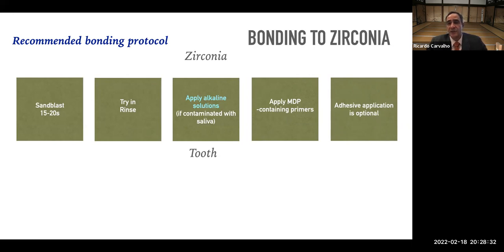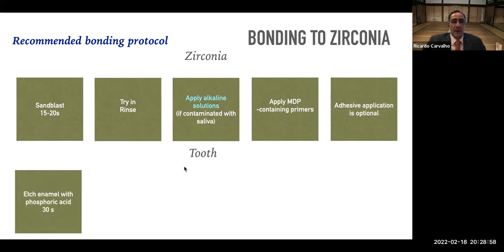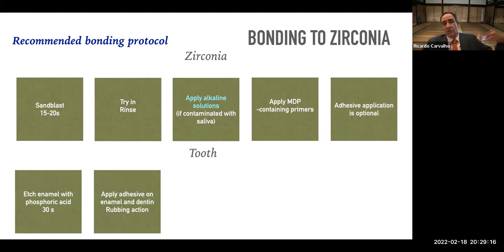For zirconia, I do not have these porosities on the surface. I do not use acids to increase porosity. So I don't need necessarily the application of the adhesive. I can do the cementation directly with the cement. And as you know, for zirconia, you can even use a glass ionomer cement, for instance, if you want to, but resin cements are always recommended. Then I treat the tooth the same way. Usually, if I have enamel still available, I etch enamel with phosphoric acid for 30 seconds. And in most cases, I have dentin, and then you're going to have to decide whether you prefer to use total etch on the tooth or self-etch adhesive. It is really up to your preference in that sense.